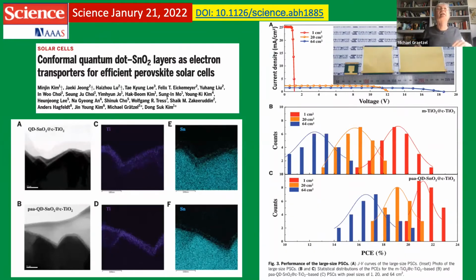And so yeah, this was a very nice discovery with the Korean group, Professor Kim and the 2 Kims, and also our colleague Hagfeld. And it shows that if you use a quantum dot tin oxide layer, you match better. The quantum dot shows a larger band gap than the normal tin oxide nanoparticles. And so the quantum size effect increases the band gap. And so for the tin oxides, mainly the conduction band moves up to a higher level, and that matches perfectly the perovskite. And so there we can get better extraction of the carriers and better photovoltaic performance. And yeah, so it's very important to also work on the electron selective contact.